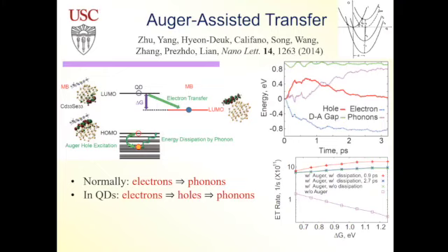But in nanoscale systems, you have a fairly interesting combination of two properties where you have high density of states and also strong Coulomb interactions. In molecules, you have strong interactions between charges, but states are few. In bulk semiconductors, you have many, many states, but Coulomb interactions are screened. But in nanoscale materials, you have both.